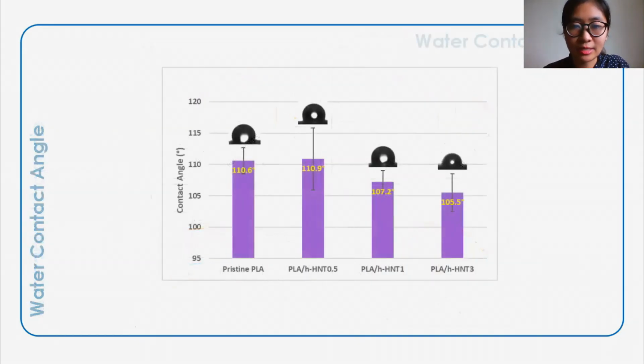Next is the surface wettability of electrospun fiber mats, so the average water contact angle was recorded. The electrospun PLA sample, known to be a hydrophobic synthetic polymer due to a lack of polar functional groups, exhibited a water contact angle of 110.6 degrees. The effect of increasing h-HNT content on the polymer matrix resulted in a slight decrease in contact angle. However, since the measured contact angles for the electrospun fiber mats are greater than 90 degrees, the wettability of the mats indicates a hydrophobic surface.